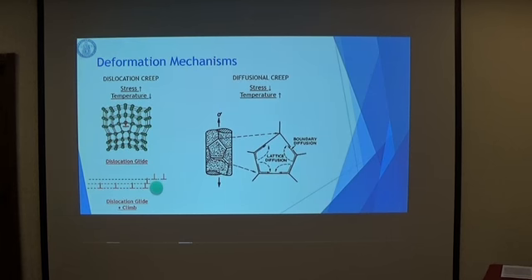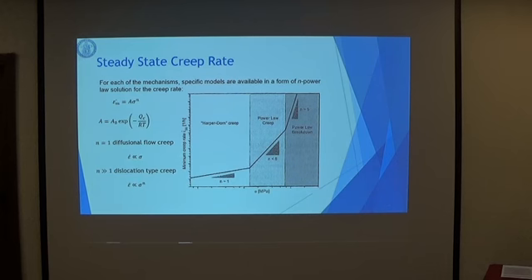Depending on stress and temperature, there are mainly two different deformation mechanisms. So we are talking about dislocation glide, or dislocation glide plus climb, or diffusional creep. For each of these mechanisms, there are specific models available in the literature, most of them in the form of an n-power law solution, like this one, where the term A can be made explicit for the temperature in terms of Arrhenius law. In case of diffusional flow, there is a linear dependence of the creep rate on the stress, while talking about dislocation creep, the strain rate is going to be proportional to the power n of the stress.